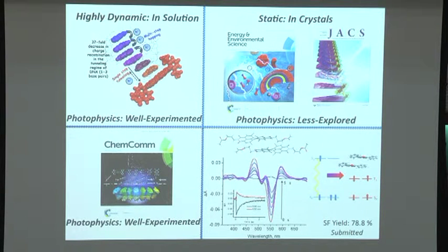But there are other topics of interest that we recently developed. If you have a pyrene molecule, as available from Aldrich, and you crystallize it, you get something called herringbone packing, where you will have a 90-degree angle between the 2 adjacent pyrene chromophores. If you shine light onto this material, it appears like a blue fluorescent material.